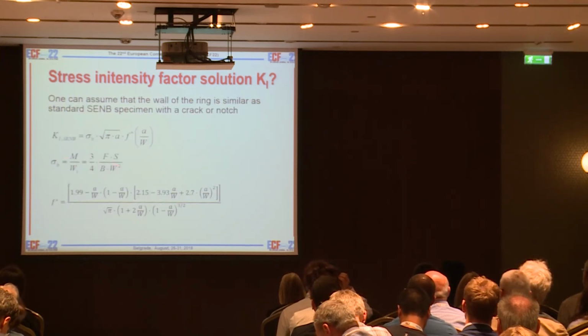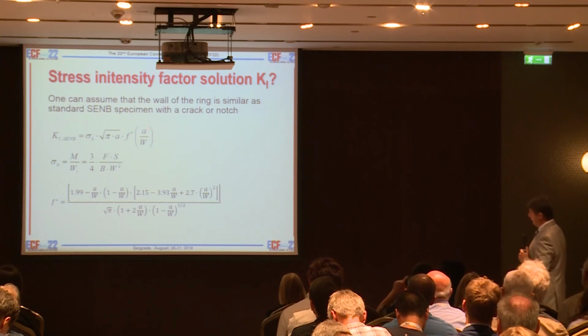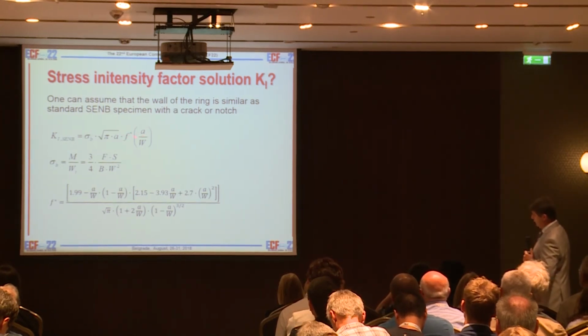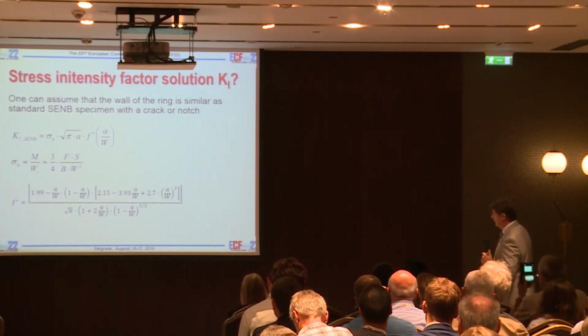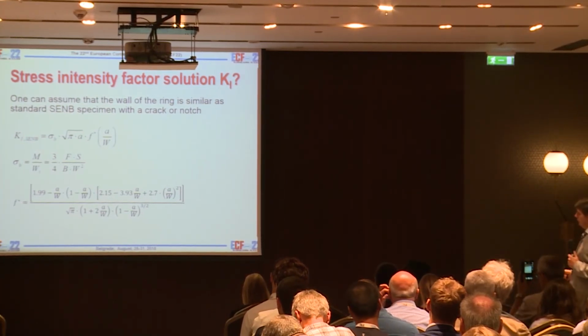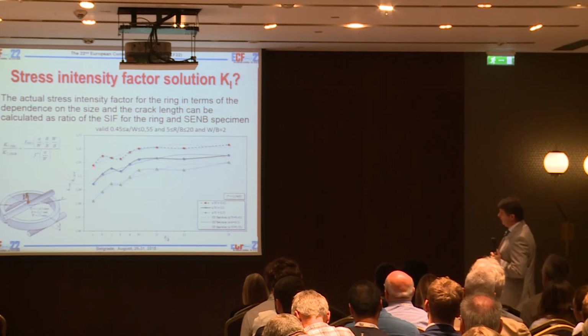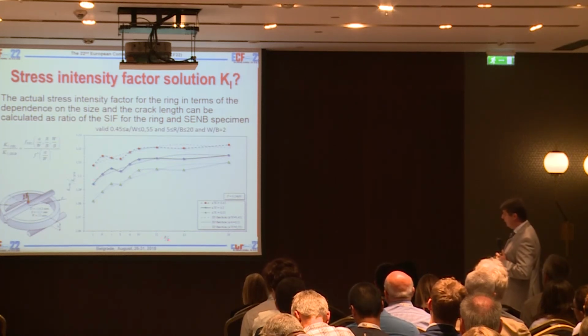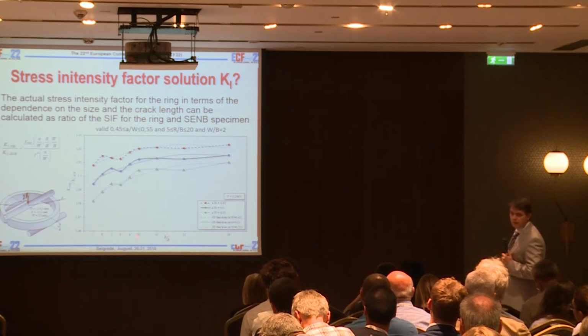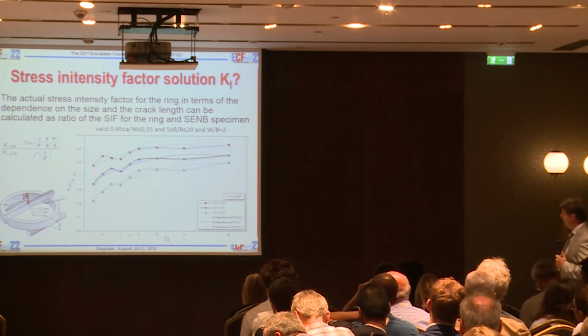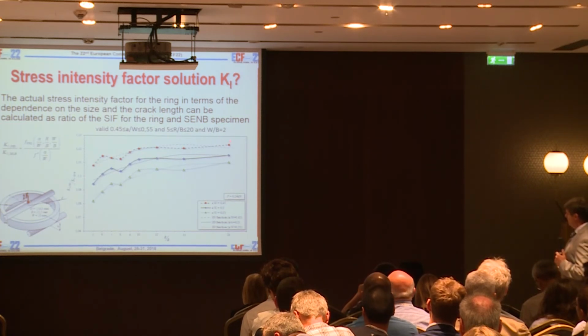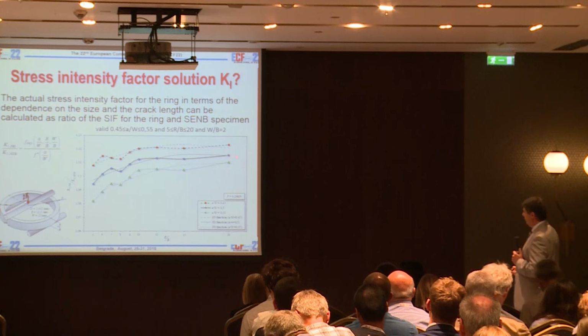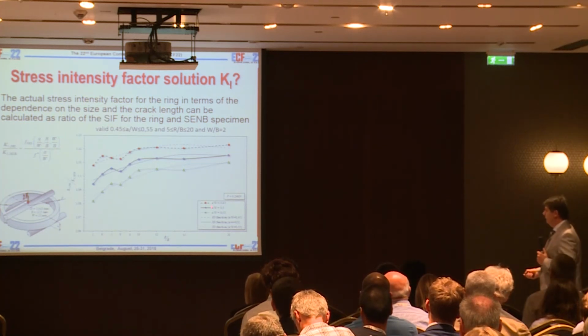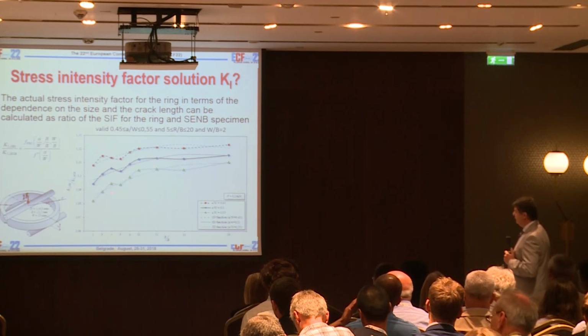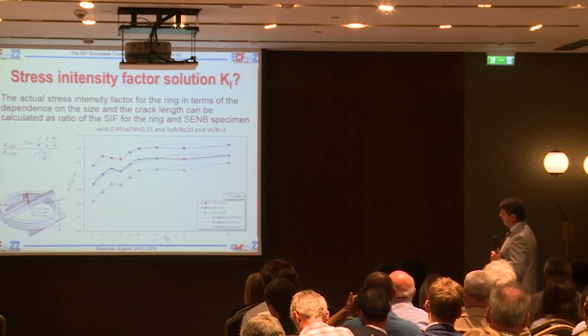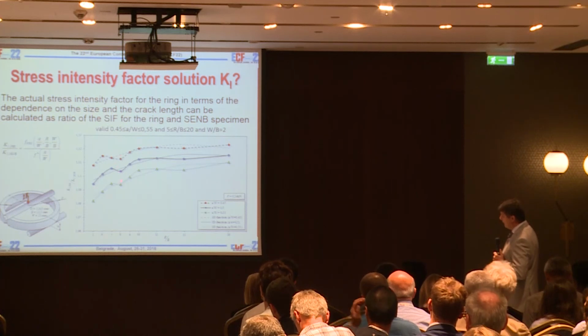So here, we use this formula for F star, which you can see here. So these values can now be compared with the shape function of the pipe specimen. And what we did, we calculated the stress intensity factor at this point and put here for different R over W ratio. So R is outer diameter. And this is one line. This line belongs to 0.45, this belongs to 0.5, and this green dot is 0.55, like that. So here we have around 8. With the difference between R and W, we have a small drop.